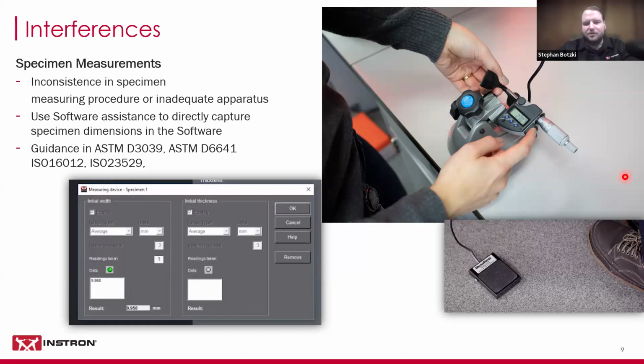In general, if we're looking at composite testing standards like ASTM D3039 or D6641, which are again very popular, they typically require you to measure the width and the thickness at 3 different locations within the gauge section. And again, that's where we want to have our failure, right? The gauge section of the specimen. So that's also the area where you will do the 3 different measurements for width and thickness, and then you average those, and that will be what you use for your values.